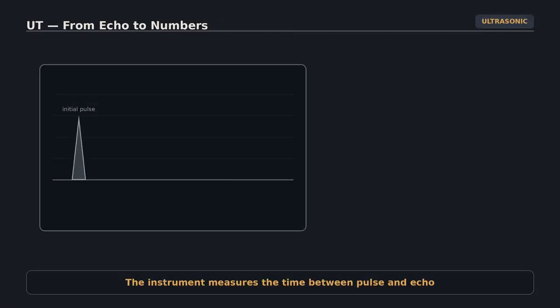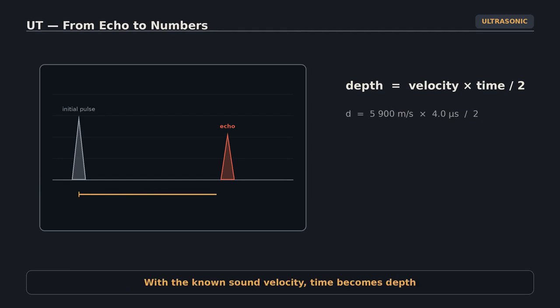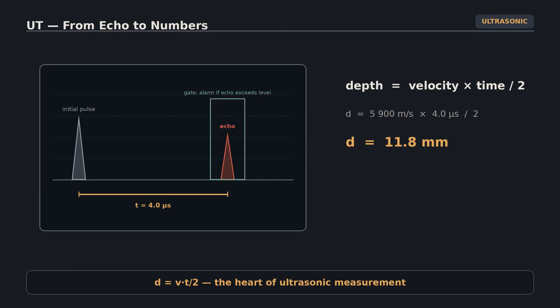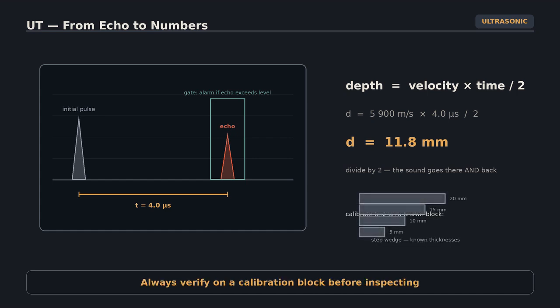How does an echo become a number? Measure the time, for microseconds. Depth equals velocity times time divided by 2, because the sound went there and back. That is 11.8 millimeters. And before every job, verify on a calibration block.